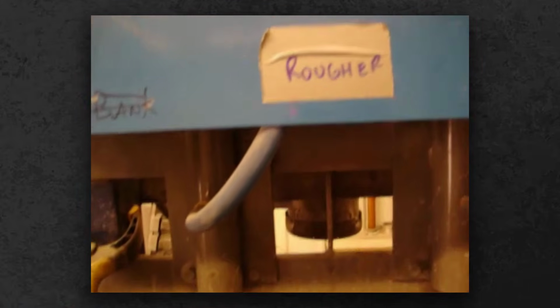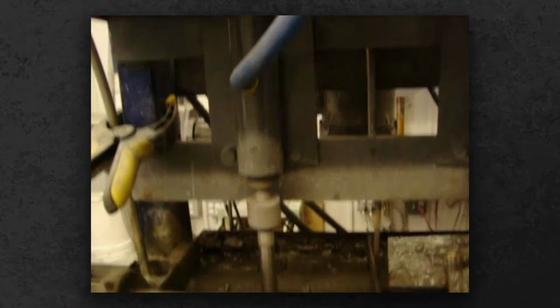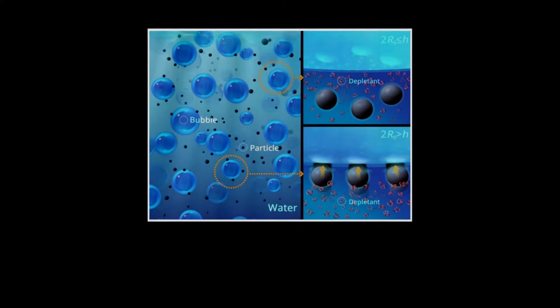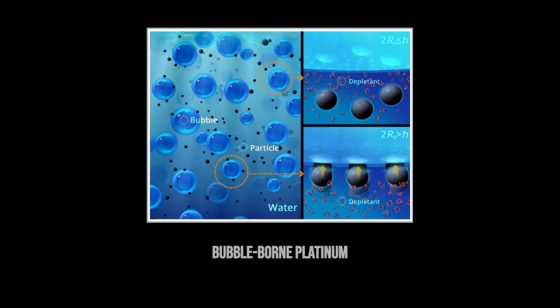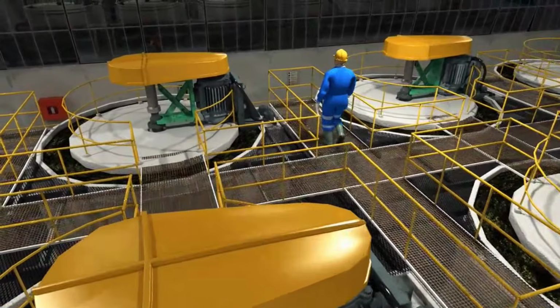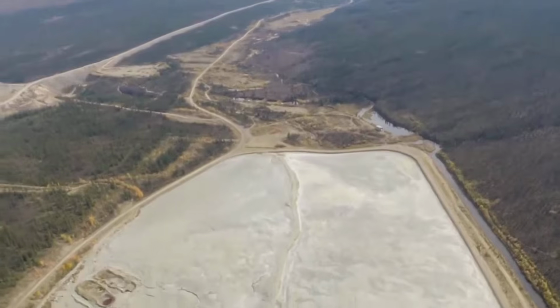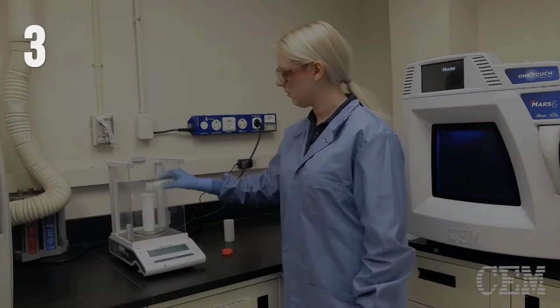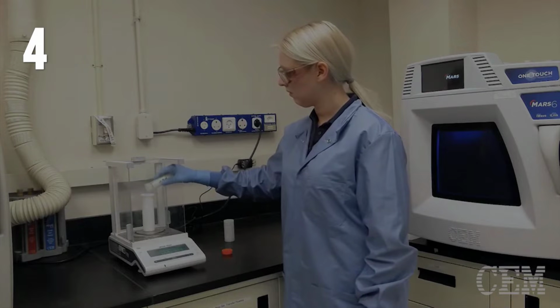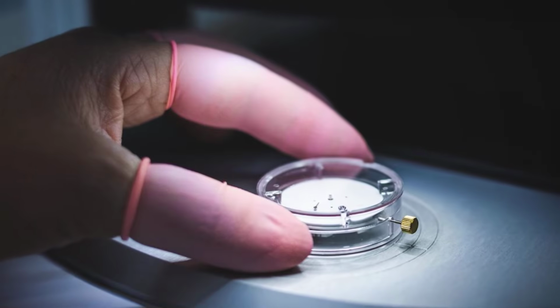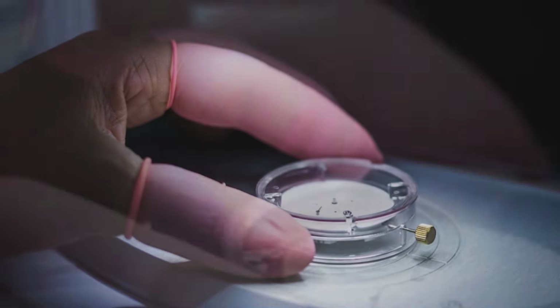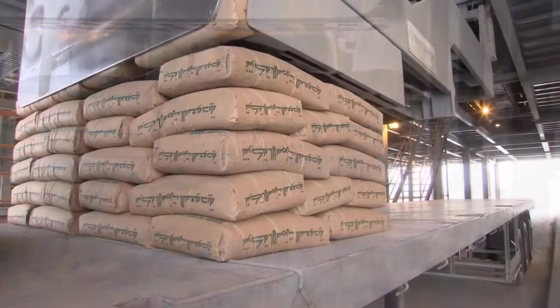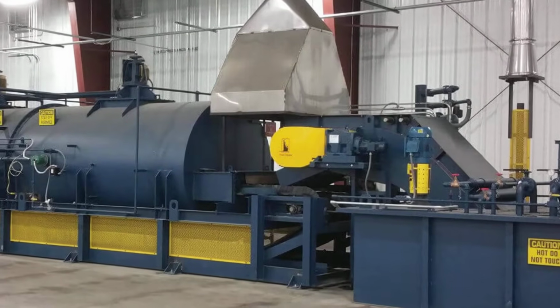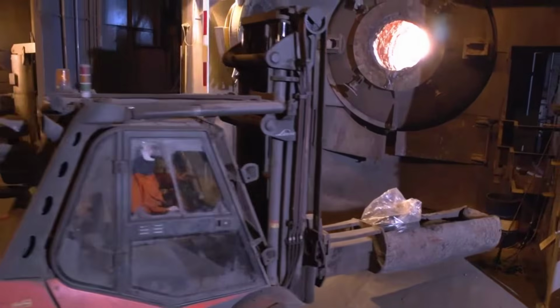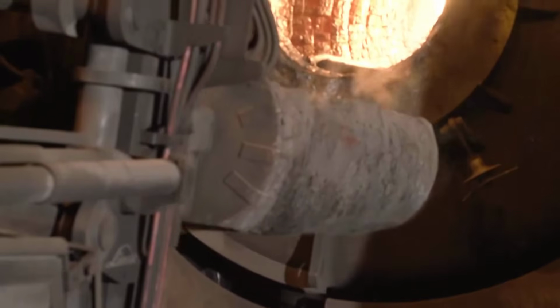Froth flotation begins as air bubbles and chemical reagents are injected into tanks. Platinum-bearing particles cling to the bubbles and rise, forming a shimmering froth at the surface. This concentrate is skimmed off, while the waste sinks and is discarded. Even now, the precious metal is measured in grams per ton, still a far cry from the purity required for the market. The concentrate, loaded with platinum and its sister metals, is now ready to enter the smelter, where fire and chemistry will begin the process of true separation.